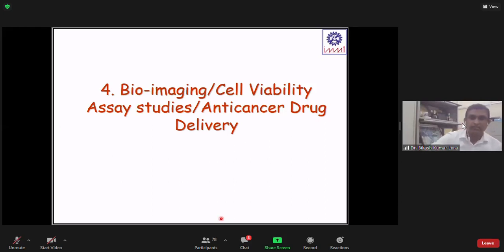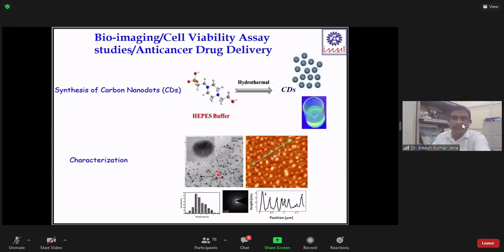So in this case, we developed some kind of carbon quantum dots, carbon nanodots, you can say. So this is how we synthesize these nanodots. HEPES is a kind of buffer molecule, a simple biomolecule. We tried a hydrothermal synthesis process, and with that, we were able to develop very tiny carbon nanodots, less than 5 nanometer. You can see carbon quantum dots. When put in UV light, you get some luminescence properties. So these are the carbon nanodots we synthesized.